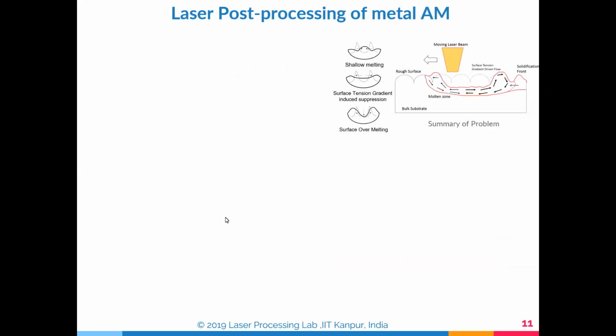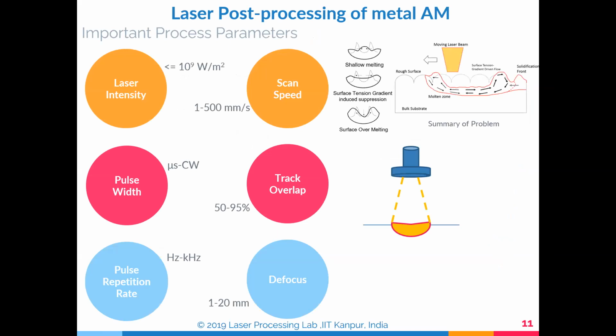When talking about laser polishing, these are some of the important parameters. One is the laser intensity, which should be 10 to the power 9 watts per meter square. Then you have a scanning speed of up to 500 millimeters per second. Pulse width is from microseconds to continuous wave. Track overlap is 50 to 95 percent. Pulse repetition rate is hertz to kilohertz. Then you focus or defocus; this is a defocused one. So when we have a moving laser trying to create, this is a rough surface.